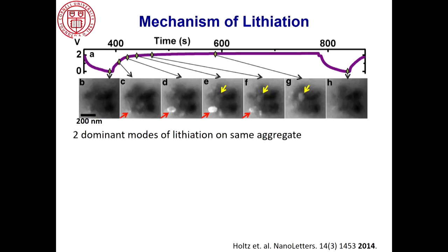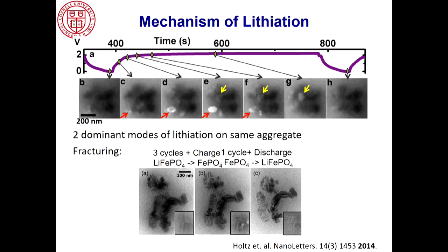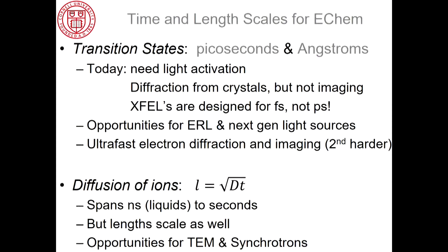If you track the cycle, here's a nice particle building up a core shell, and then eventually, wait, where'd it go? It, in fact, cracked and broke off the material because the lattice constant is so different. And by the end of the cycling, you've actually fractured and pummeled these particles. This is one of the other reasons why you need carbon around lithium iron phosphate, to keep it all together after it's cracked and cycled. From my experience with MBE growth, 3% lattice mismatch is huge and usually leads to fracture. And that's supposed to be a low strain material.